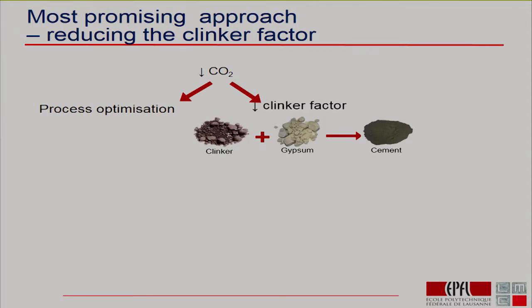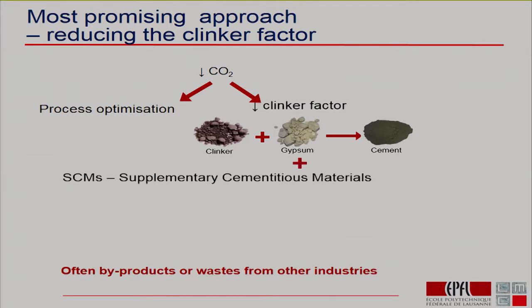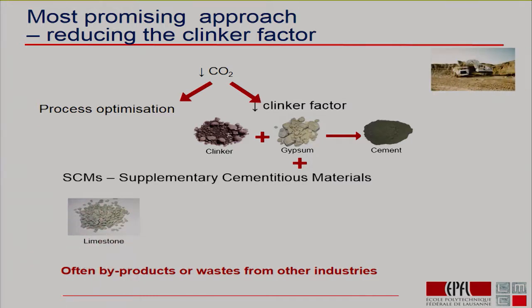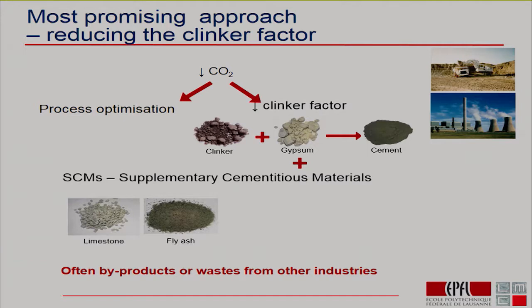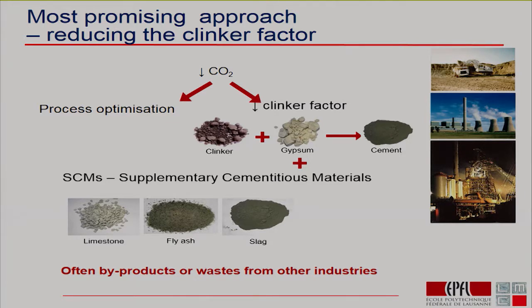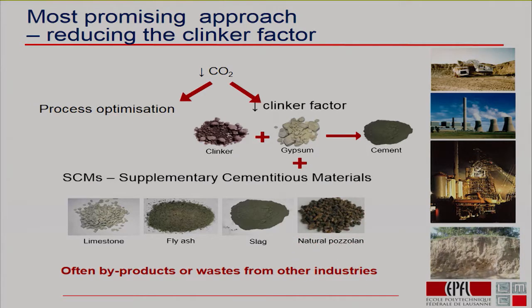So what does reducing the clinker factor mean? It means that in the past, 50 years ago or so, we had clinker, which is the stuff that comes out of a cement kiln, and we ground it with a bit of gypsum, calcium sulfate, and that gave us cement. And nowadays, we introduce increasing amounts of what we call supplementary cementitious materials, and these are things like fine limestone. This is things like fly ash that comes from burning coal to produce electricity. This is stuff like slag, which comes from blast furnaces where we reduce iron oxide to make steel. And also we can have some natural pozzolans. So we have all this family of materials which we can now interblend with the cement to reduce the amount of the Portland cement clinker.